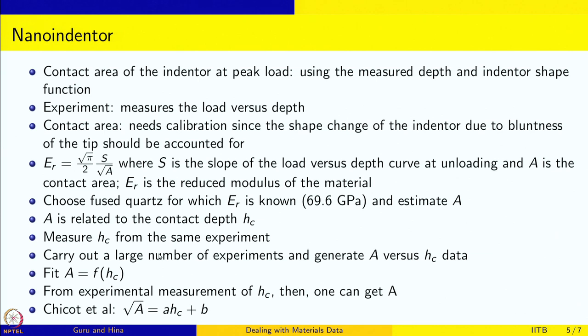You can generate a large number of experiments in which you measure Hc and A using a known material, develop a relationship between A and Hc, and then use that to do analysis on a new material. The idea is to carry out a large number of experiments, generate A versus Hc data, and fit A to some function of Hc. From an experimental measurement of Hc on a new material, one can get A and then use it to get the mechanical properties of the material. Chicot et al. give root(A) = a·Hc + b, so we have to determine the slope and the intercept.